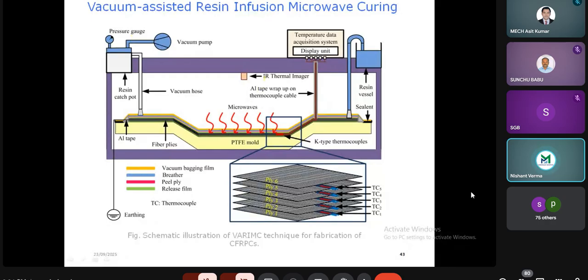And this IR thermal imaging is used to quantify the temperature. So why is temperature monitoring important? Because we have something called glass transition temperature, or a curing temperature. So we need to heat till the achievement of that temperature. So after the solidification of this, the vacuum bagging film is peeled out, and the specimen can be made. So a similar technique of temperature measurement we have used in this technique also.